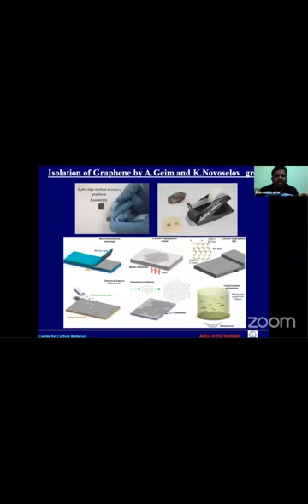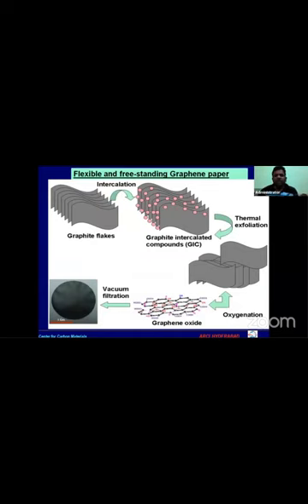There are different techniques. Initially, those who won the Nobel Prize used the Scotch tape technique, where they took a very strong adhesive tape and peeled off from a HOPG, and then tried to isolate what was there, characterize it, and found that a single layer of graphene had come out. Then people have tried even the silicon carbide template method, dissolving the silicon at high temperature, and then getting the graphene. People are exploring different techniques, but we are using it in a different format.